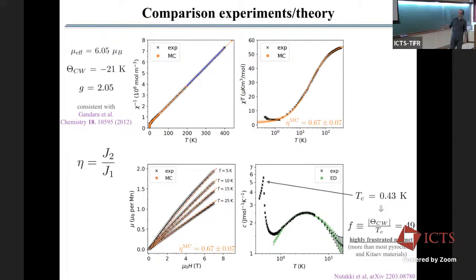So this ratio of J2 over J1 of roughly 0.67 matches very well with DFT estimate. So the DFT ab initio calculations done by Alexander Tcherlin tell us there is some range of degree of freedom about the absolute value of J1 and J2. So depending on the parameters of DFT, we can change that a bit. But the ratio between the two found in DFT calculations is very close to the one we find in classical Monte Carlo simulations. And if we compare it to what we used in hexagonalization, it's not so far either. Hexagonalization is a bit further away, but it's not surprising because this is really a very rough approximation to reproduce the high temperature bump. So we don't expect these parameters to be really precise. But still, ED gives us something which is of the same order as classical Monte Carlo and as DFT calculations.